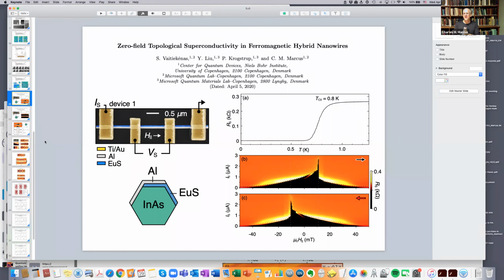You know, it seemed like one thing too many: europium sulfide and superconductors and a spin orbit atom. It just felt like someone's head was going to explode. But it would be a way, and I think that there is work going on. Forget about the europium sulfide for a second. But if you want to put the thing in a large magnetic field, I think that you can put these platinum atoms on the surface to make the critical magnetic field higher from Elliott-Yafet spin orbit coupling. But I don't think that it helps you in the Majorana world, except possibly to give you a larger critical field. Sure. But as you saw from those gap pictures, it reduces the gap. So it's this funny thing. Bc goes up, the critical field goes up. Tc and the gap go down, or Tc is almost constant and the gap goes down.